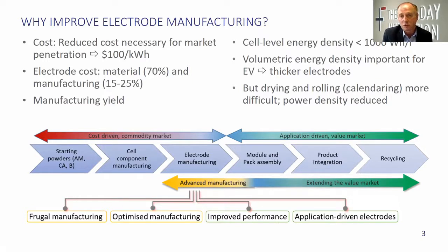There's also a performance driver. We need to be able to store more energy in a fixed volume — for example, the space available within an electric vehicle platform. A simple way to do that would be just to make the electrodes thicker and minimize the amount of copper and aluminium foil. But if we do that and make thicker electrodes, they're actually more difficult to dry and to calender — roll them to the right thickness — and also they become sluggish and don't deliver the right amount of power. The schematic shows the basic steps of the slurry casting process: we mix the active material, the carbon, and the binder together; we coat them to form the electrode; the electrode is formed into cells and integrated into the electric vehicle platform; and we must be mindful of what we do with it at end of life.